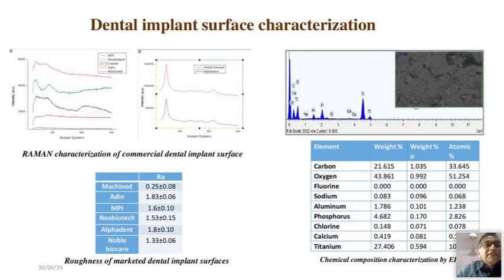We started with Raman. Also, we did XRD and XPS or EDX to find out the elemental composition of our machined implants, Adin implants, MPI, Neobiotech, Noble Biocare, and we found that most of the roughness is lying between 1.3 to 1.8 Ra. Ra is the average roughness. Whereas when we do the machining, it is only 0.25 roughness. So that means we need a technique to make the surface rough on the implant, and being circular, we have